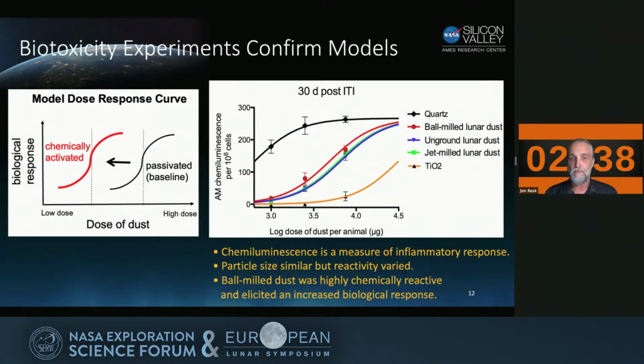And we measured the inflammatory response of the cells that responded to this injection of dust in the lungs of the rats. And the short story is that that material, which was more highly chemically reactive as assayed by the hydroxyl radical scavenging assays we've used, was more biologically toxic. Although the difference was small, it was highly statistically significant in terms of it being more impactful in the lungs of the rats. So this is a very important observation that we had made here, and it further emphasizes the importance of chemical reactivity as it relates to its biological effects, in this case, in the lungs of rats.